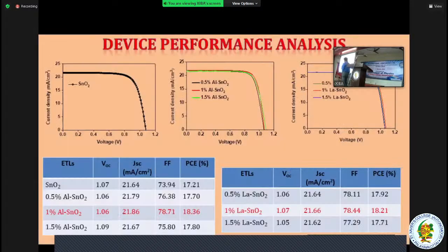So this slide is for pure tin oxide, and initially we tried aluminum doped tin oxide with different composites: 0.5, 1 and 1.5. In this, we got a very good result for the 1% aluminum doped tin oxide. It's 18.36%, the final PCE value. Then VOC, JSC, fill factor, all the values are given here. And similarly, this is for the lanthanum doped tin oxide. In this, the 1% lanthanum doped tin oxide gives us a very good result of 18.21%.